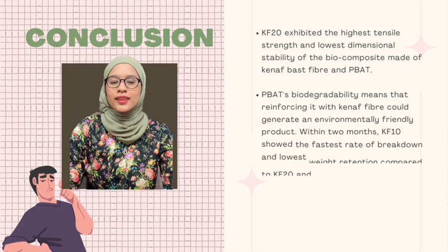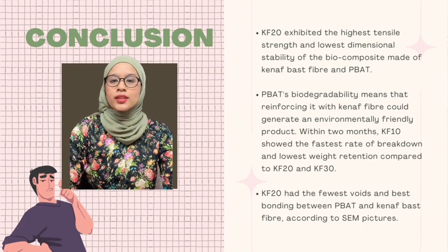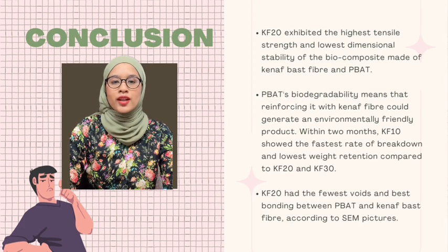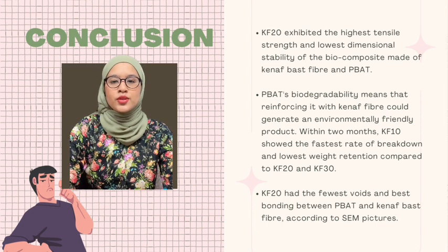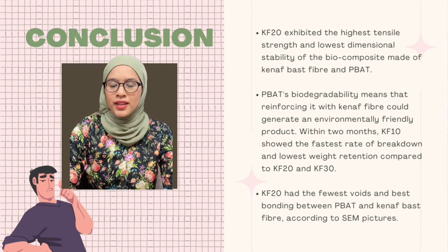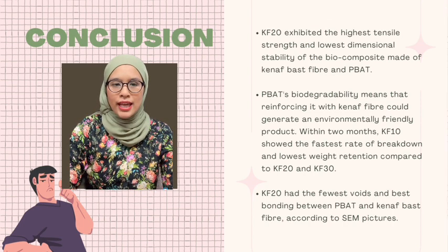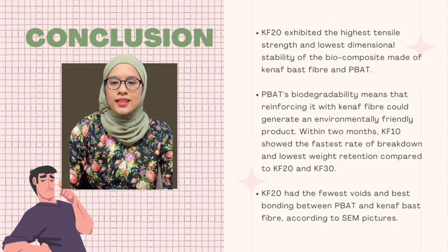In conclusion, in these studies, various tests were conducted on a biocomposite made of Kenaf Bast fiber and PBAT. The results showed that the biocomposite has high potential to be an environmentally friendly product, thanks to PBAT's biodegradability and the reinforcing effect of Kenaf fiber. The best results were found with a specific ratio of Kenaf fiber, which is the KF20, had the highest tensile strength and lowest dimensional stability compared to other biocomposites.